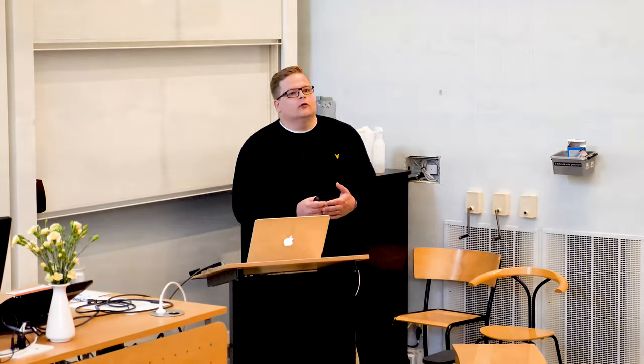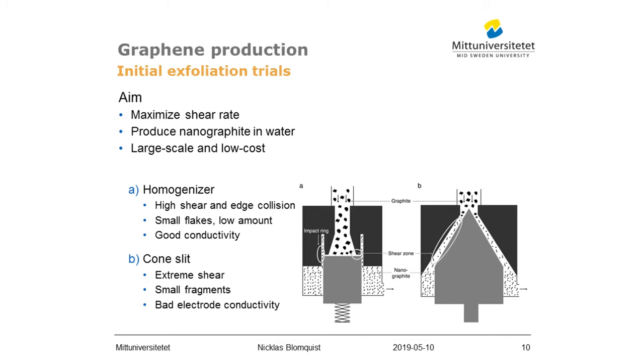In this thesis, I present a new way to exfoliate graphite to multilayer graphene and graphite nanoplatelets. The aim for this work was to maximize the shear force, the shear rate, and try to avoid the edge collision. I also wanted to produce these nanographites in water on a large scale and at a low cost.